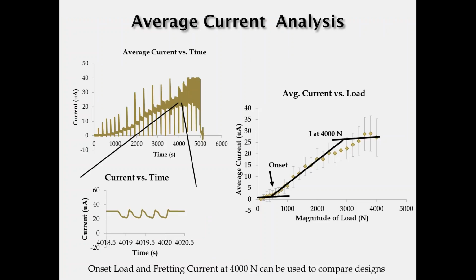Now, simultaneously, we can capture the currents that are generated by the fretting corrosion mechanism at the junction, and we can look at them as a function of the cyclic load magnitude, this curve on the right, or just plot it out over time, capturing 1 second or 1.5 seconds of data periodically throughout the entire course of the test, and that's what this left-hand plot is showing.